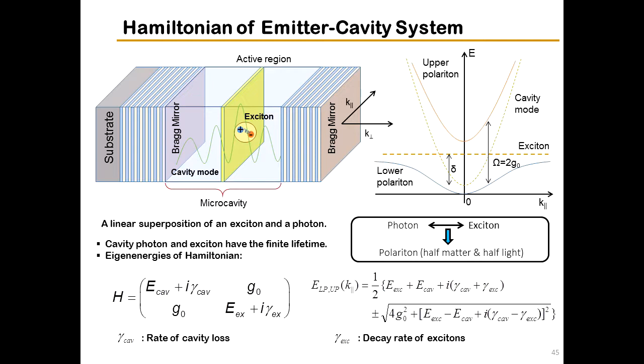Now, what do we do with this? If you look at the polariton dispersion relation, this is in K space, of course. When we excite the system, we form excitons from electron-hole pairs, and the excitons are scattered by phonons. These exciton polaritons, which are mostly excitons here, are scattered by phonons and come down. At the same time, they're emitting photons from the microcavity, and they come down by scattering.